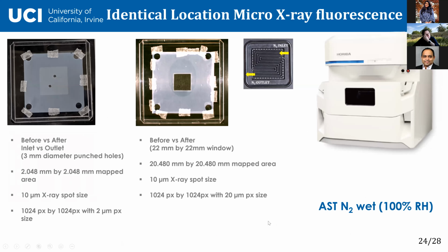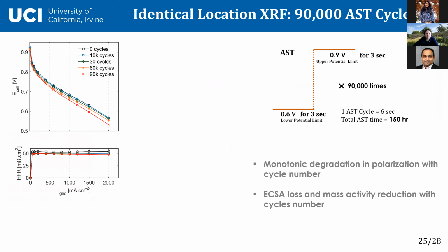And my student developed this identical location micro XRF technique. So we have a local Horiba instrument where we can use 10 micron capillary to really map platinum loading. So this was kind of exciting. No one has done this before. So this time we used 90,000 cycles. That's kind of heavy duty accelerated stress test protocol.